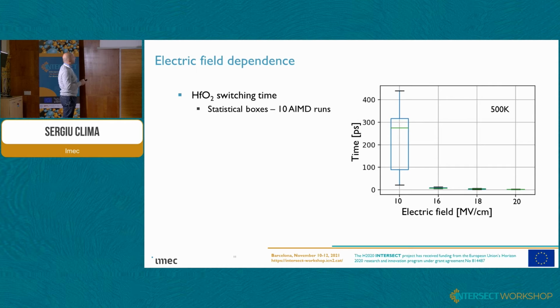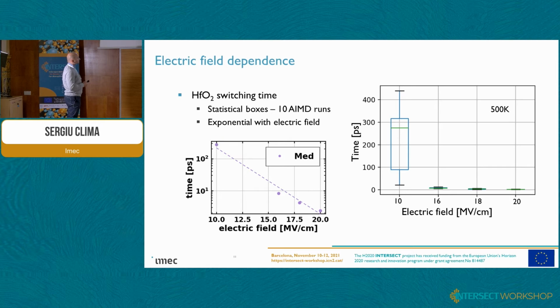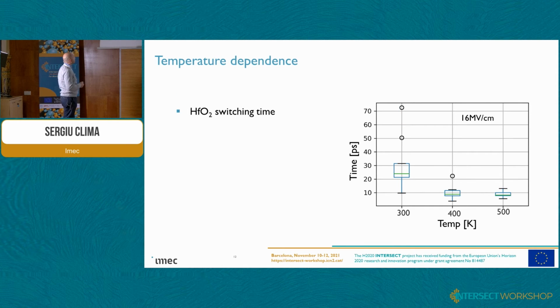You can see that the lower the electric field, the wider the spread in time, and the higher the electric field, the more deterministic the switching nucleation is. And here I plot the median data points to show that we have quite an exponential behavior of the switching, which fits rather well at these high electric fields with Arrhenius behavior.